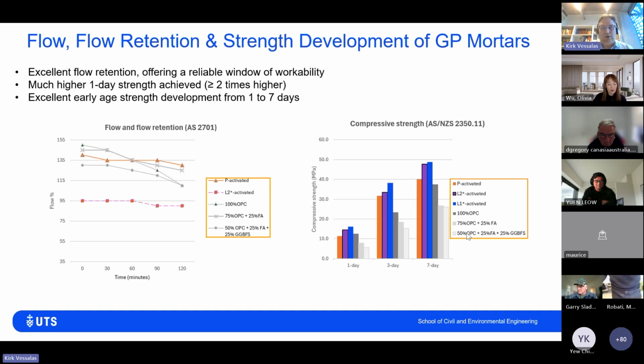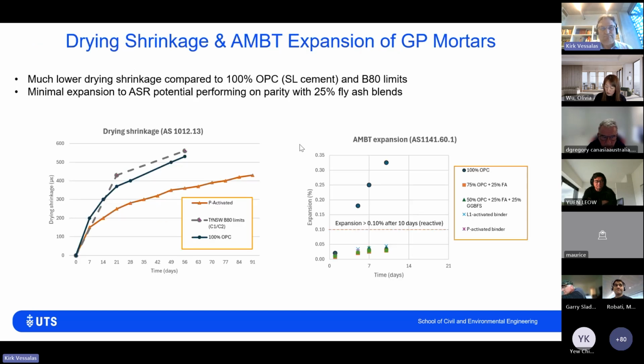And particularly if we're looking at a low carbon concrete, a ternary blend that has 25% fly ash and 25% slag, the strengths that we're getting here after 1 day are almost in excess of 2 times higher than our conventional systems, which is very good. Also, there is very good strength gain moving from 1 across to 7. So 1, 3, and 7 again, compared to the conventional Portland cement systems. And all our testing has been done in accordance with the various Australian standards and equally between mortars and concretes.